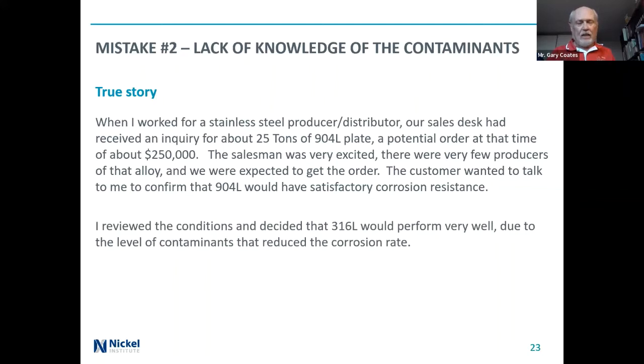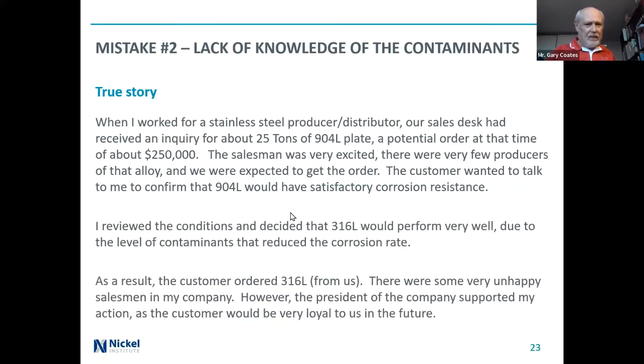Well, as it turned out, I reviewed the conditions. The acid had a lot of oxidizing contaminants in it, and I decided that 316L would actually perform very well there, because they guaranteed that those contaminants would always be there. This was just part of the process. They were always adding it, and so I suggested that he could use 316L, and as a result, he did buy it from us. Actually, there were many more competitors for 316L, but of course there were some unhappy salesmen in the company because there was this big order that they were hoping to get, and 316L is maybe 1/3 the cost of 904L. However, the president of the company actually supported my action, and the customer became very loyal to us.